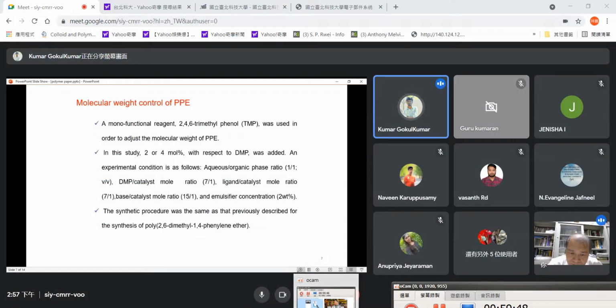It uses a 2 or 4 molar ratio, with the DMP added in the experimental conditions. The aqueous to organic phase ratio is 1:1, the DMP to catalyst ratio is 7:1, the ligand to catalyst mole ratio is 7:1, and the base to catalyst ratio is 15:1. All conditions use an emulsifier concentration of 2 weight percent of the system. The synthetic process mainly focuses on polyphenylene ether.